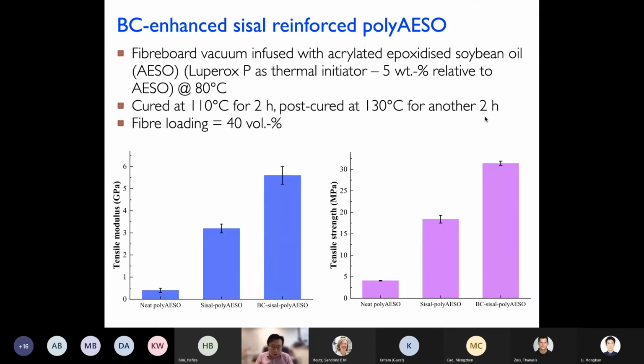At a fiber loading fraction of 40%, we are able to see a big improvement in modulus just by introducing sisal fibers alone. But with that added 10% bacterial cellulose, so you have a nanocellulose enhanced natural fiber reinforced polymer composite here, you are able to push the tensile modulus up further from about 3.5 gigapascal to almost 6 gigapascal, just with that 10% introduction of bacterial cellulose into the system. Similarly, in tensile strength, you observe the same trend as well. The introduction of that bacterial cellulose and nanocellulose into the system pushes the tensile strength up in the final nanocellulose enhanced sisal fiber reinforced polymer composites in this case here.